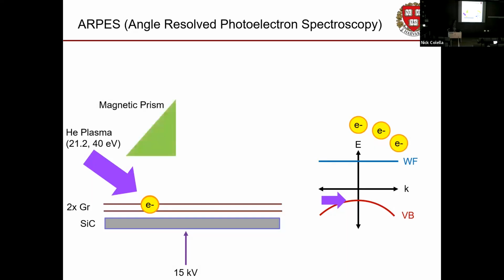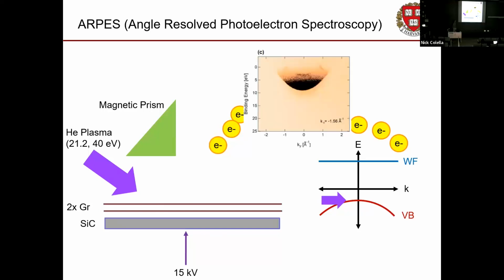Which means that if we put something that separates out radiation by its energy, which is a prism, for electrons, that's a magnetic prism, for light, it's a glass prism, then they're going to get separated out by energy the same way as before. And that means we can make a little map of the energies and, as it turns out, the in-plane momenta